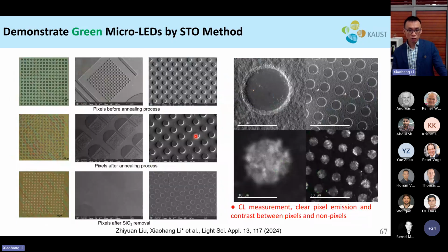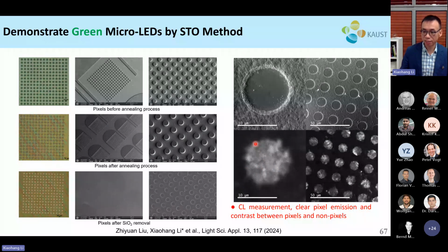And then we also study the photoluminescence, because under photoluminescence we want to examine in close proximity the light distribution across the pixel, especially near the edge, right? As you may recall, we discussed the rapid decrease of light intensity near the edge, right? But from our study, we found that the light distribution across the mesa is actually relatively uniform, right? So we actually have a much reduced side effect.